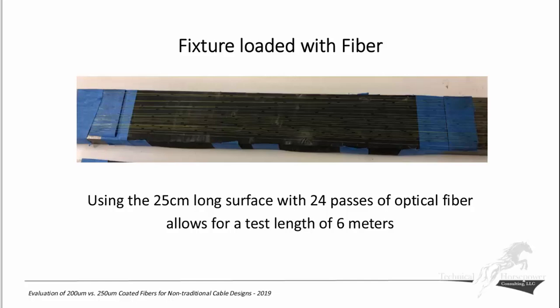And to make sure that the upper platen did not impinge on any of the tape that you saw there, only on the actual surface, so that we didn't crush edges of the fiber and add additional strain. So we were very concerned about that. But on a production basis, I would clearly build a fixture where I had the 24 slots on either side milled in so that I could lay this thing in much more easily than doing it by hand and physically chasing each one to make sure there was no crossover point. That was quite an interesting process to do.